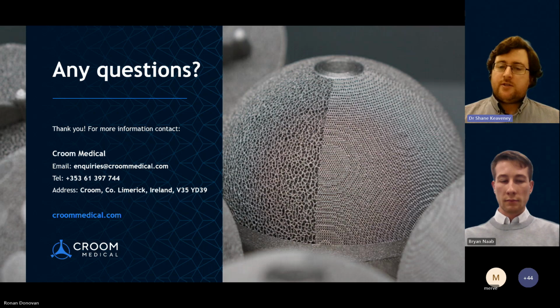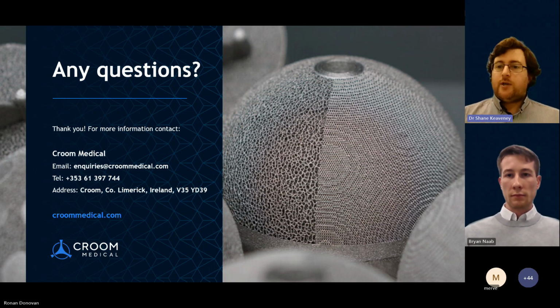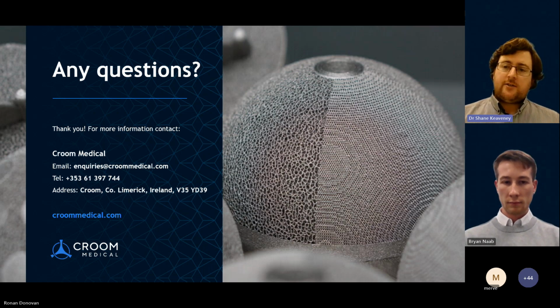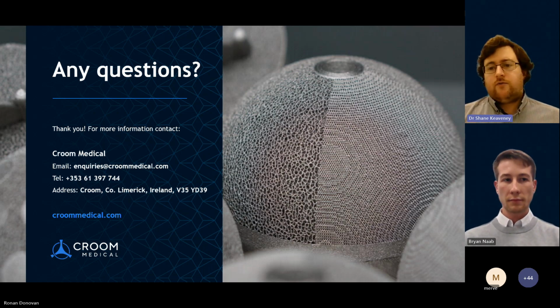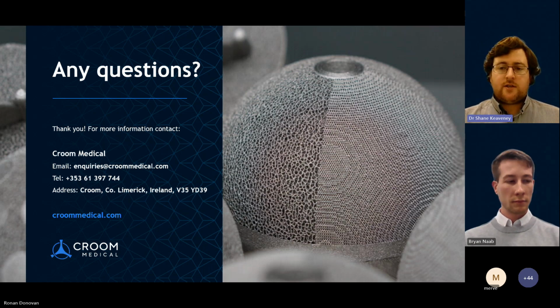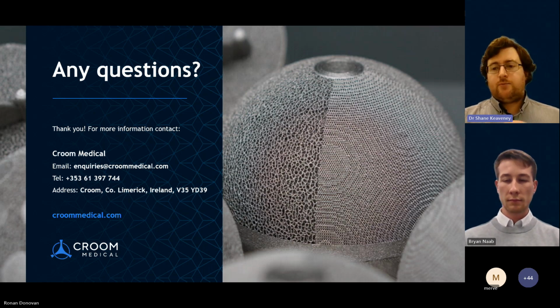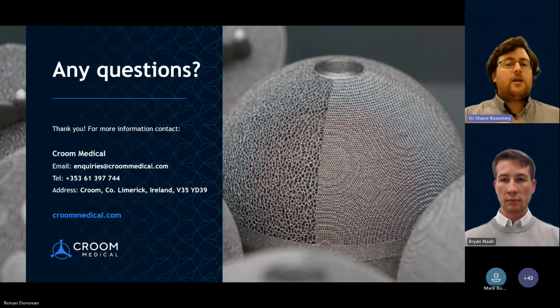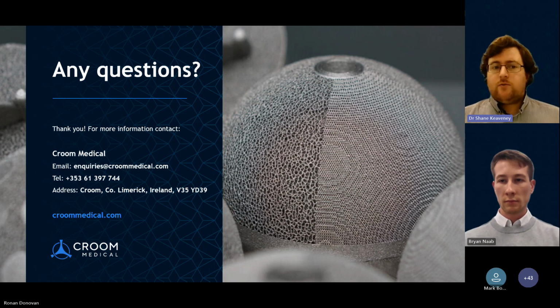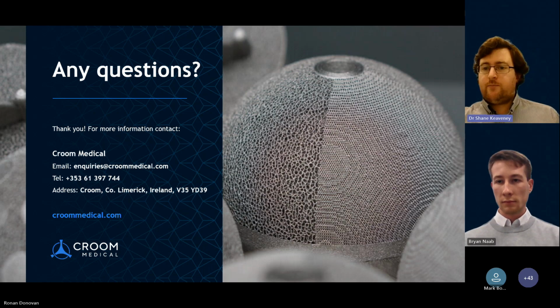And then on some of our other systems, like the M2 system, for instance, we typically don't really design the lattice structure if we're looking for thin beams. So if we're looking for, say, 100 microns to 200 or 250 microns, we don't model that. We might model it as a constant size. And then again, we change the print parameters. But if we go above, say, 300 microns, we might start to model the size. And typically the deviation can be quite minimal. We might be talking 20 microns or something like this above, but it starts to come down to your material, your print parameters. There's quite a lot of influencing factors in this. So it's a very important topic.